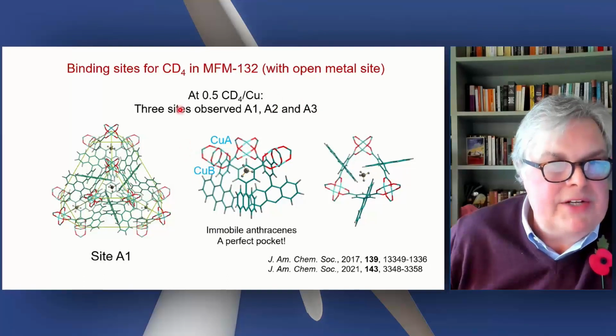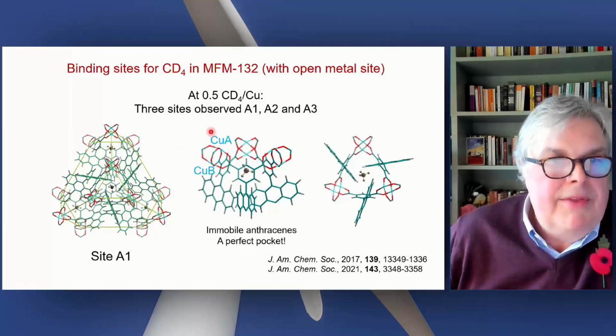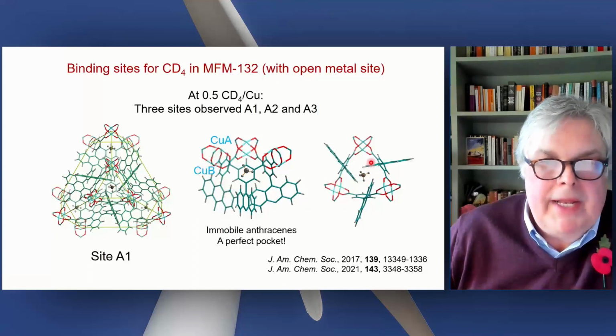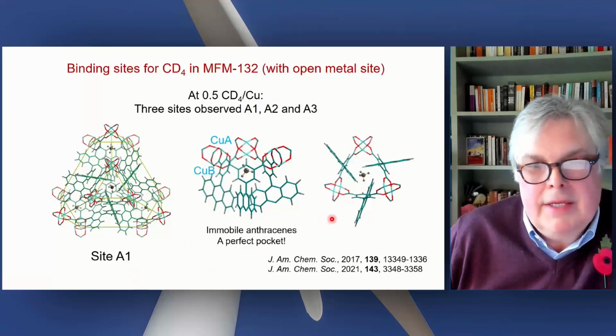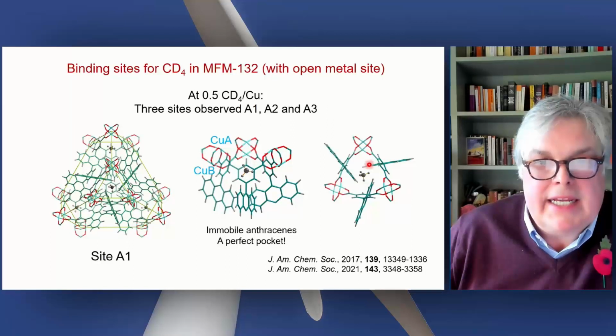This material is very interesting, the anthracene material, because the main binding site for CD4 is actually not the metal site, copper A or copper B. This is the paddle wheel you saw before, but actually it resides in this C3 symmetric pocket defined by the anthracenes. And by solid state carbon-13 NMR, and by deuterium NMR, we know that these groups do not rotate. It's very fixed. So this is a very nice location for the methane to be stored.